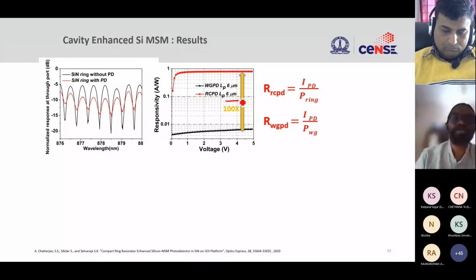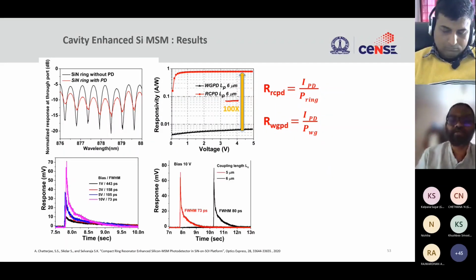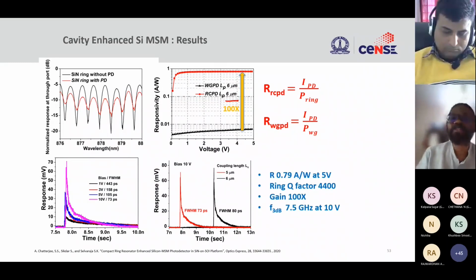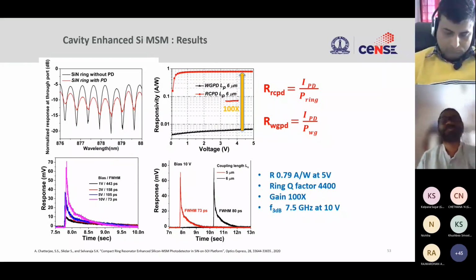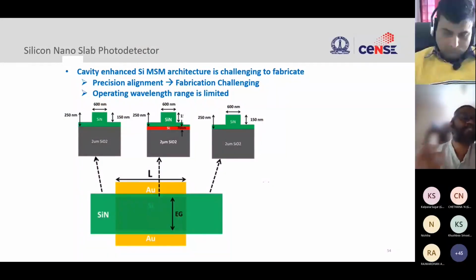And we were able to use such a small detector with responsivity in excess of about 0.7 to 0.8 amp per watt. The speed is also reasonably high, about 70 to 80 picoseconds, which gave us responsivity of about 0.8 amp per watt and speed of 7 gigahertz. These are really fantastic numbers that really excited us, and we said, okay, this is really good. Can we push this even further?